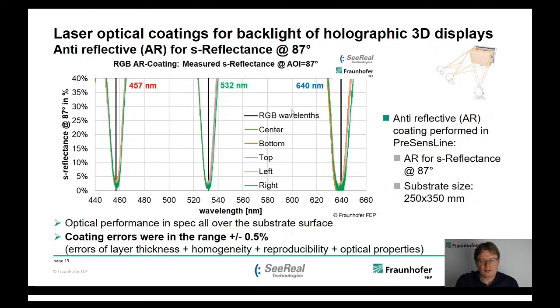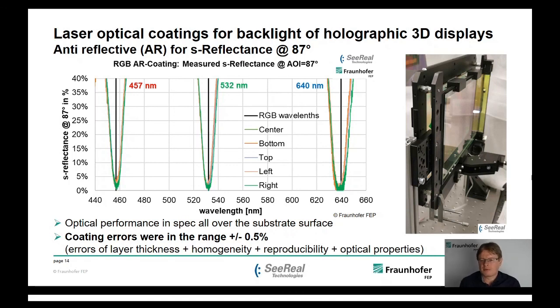So here is the optical function. The RGB laser wavelengths are shown here, and for all 3 we got a nice anti-reflective behavior. We could prove that the optical performance is in spec all over the substrate surface. The substrate size is shown here, 250 times 350 millimeters. The coating errors were in the range of plus minus 0.5%. These are errors regarding thickness, homogeneity, reproducibility, and optical properties. With this they build up such demonstrators now, and they are even working on a prototype.